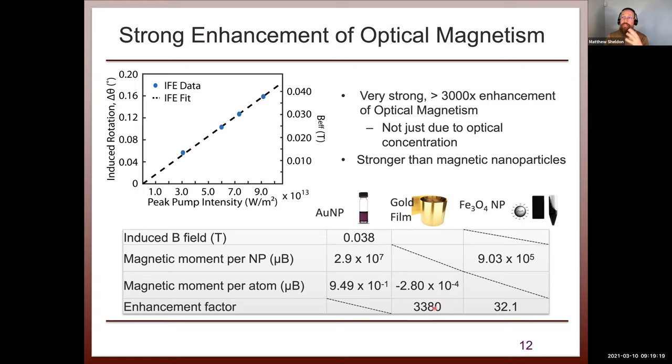And this is, I think, hopefully giving a picture that because there's this coherent resonant feedback with the driving field, by controlling the polarization state in this system, you're fundamentally changing the magnetic response of the material: the damping of the electrons, the plasma resonance, the dephasing time, all of these fundamental features that control the dynamic optical and physical behavior. These are really modified in a way that isn't just the field concentration that you often hear about in plasmonic systems. So I think this is an important insight for showing you can get dramatic, pronounced, and maybe even unexpected physical behavior out of seemingly standard gold colloid in solution if you do the experiment and set it up properly.